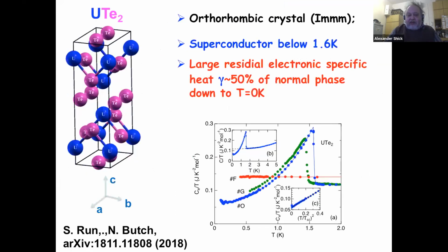And the next material I want to talk about is uranium tellurium-2. So this one is also orthorhombic. It is superconducting below 1.6 kelvins. The reason why it became so popular, and there were at some point many papers in the top journals about this material, is that when they measured the specific heat versus the temperature, they thought that this specific heat doesn't go to zero as usual in superconductors. It eventually means that only part of the electrons are in the superconducting state, while another part is not in the superconducting state.